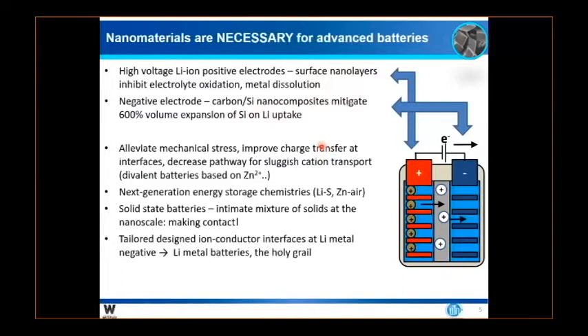But what's even more interesting going forward in next generation technologies are batteries based on zinc, so divalent ions that have sluggish transport within the solid because of their high charge. Next generation systems, which as I mentioned include lithium sulfur, zinc air, solid state batteries, and also the holy grail, which is to switch the negative electrode from something like carbon, which is what it is now, to lithium metal. And this requires designing nano layers as interfaces.